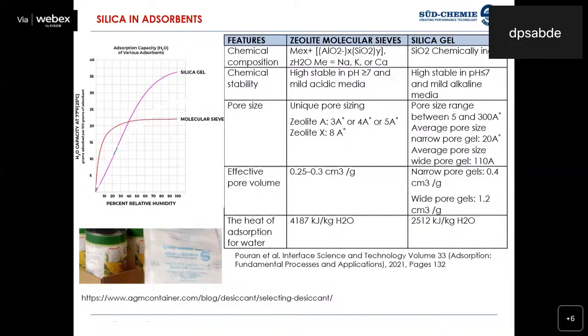Just see the plot beside the table. This is a plot of water adsorption capacity versus percent relative humidity. If you look at this plot, it's very clear that at very low relative humidity, molecular sieve based adsorbents are better compared to silica gel. Now, for silica gel, at a relative humidity above about 40, silica gel is the better option. So depending on the kind of requirements, there is a possibility to use different types of adsorbents for different applications.